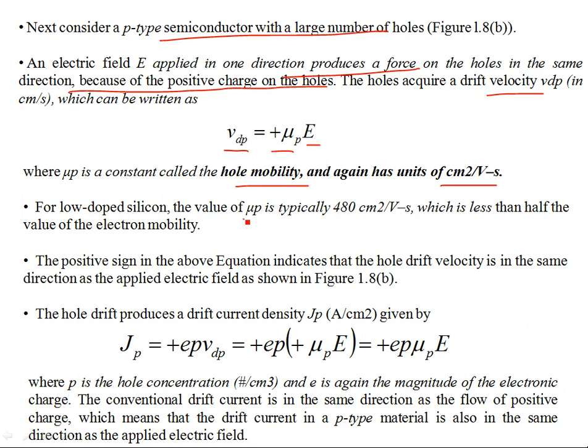But the low-doped silicon has a typical value of 480 centimeters squared per volt-second, which is less than half of the value of electron mobility. So electrons are more mobile in typical low-doped silicon, the same material. This is one thing to notice: for a small electric field, if you go on increasing it, you have larger drift velocities, and as compared to holes, electrons are more mobile. They can contribute to the conductivity of the material more than the holes. So the positive sign in the above equation indicates that the drift velocity is in the same direction as the applied electric field.